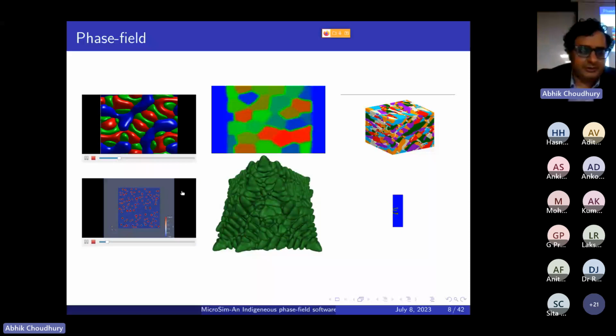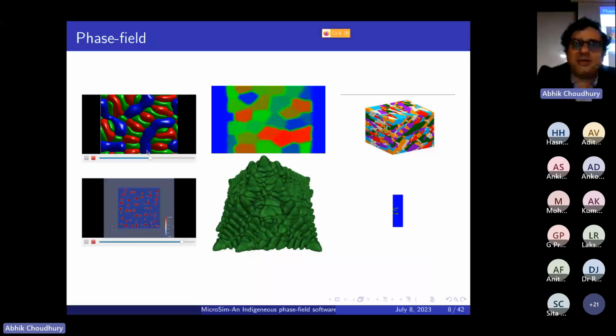As you see over here, in the top part you have three-phase solidification of a eutectic, which is essentially solidifying towards you in a directional solidification setting, and the phase field microstructure evolution is able to show you that the simulation can predict microstructure formation and pattern evolution as the experiment is progressing.